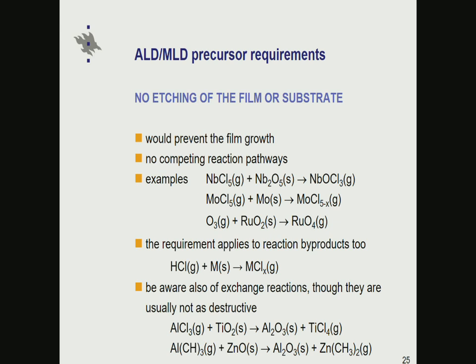And the same requirement, of course, applies to byproducts. In the case of metal chlorides, quite often HCl is produced, and that can then react, for example, with the metal. A somewhat related reaction, but not as detrimental as these etching reactions, is the exchange reaction. This means that one is, for example, depositing nanolaminates consisting of titanium oxide and aluminum oxide using, in this case, aluminum chloride. So what happens once you have completed one layer of titanium oxide and you deposit the next aluminum oxide on top of that?